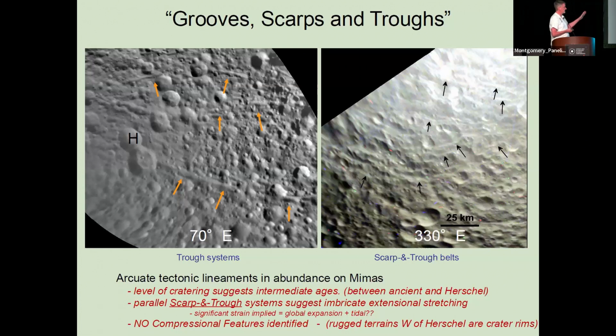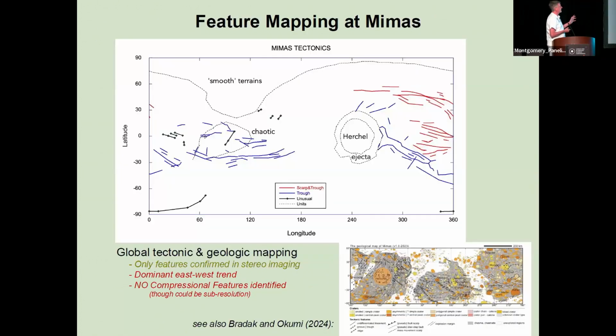The fact is that we see no positive relief structures here. We only see negative reliefs, which suggests that they're mostly extensional, not compressional. This is the map distribution of where they are. We haven't done a stress analysis on these yet, but the east-west tendency of these structures tends to support maybe either probably tidal deformation, but we haven't done the test on that yet. But the fact that they're mostly extensional suggests that maybe we're dealing with global expansion.